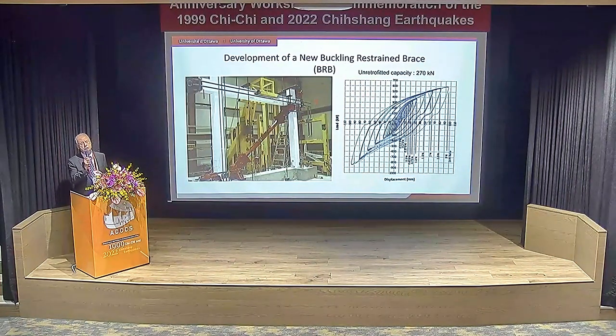2.5% drift. Obviously, if you are designing a BRB, one has to be aware of the fact that you're dealing with non-ductile frame, so drift control is important, and you don't want to allow too much drift to permit this non-ductile frame start developing failure. We did measure how much of the force was taken by the brace and how much was left to the frame, so that frame would maintain their gravity load carrying capacity, but those details I'm not presenting here.